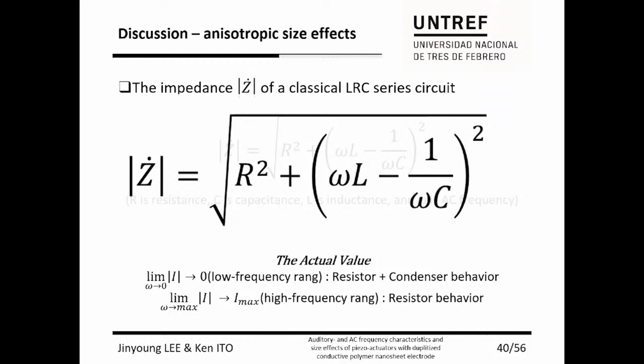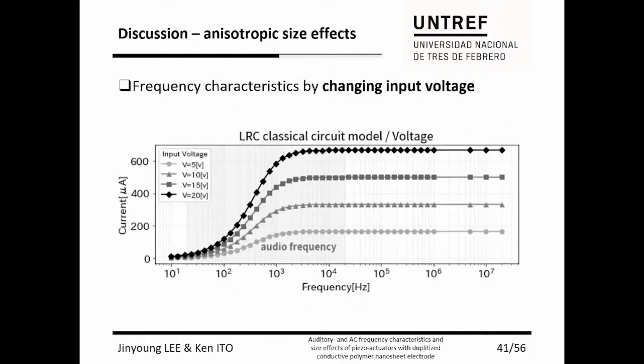In the following, we consider an RC series circuit by assigning 0 Henry to the inductor and 10 kΩ to the resistor. In the classical RC circuit model, the high frequency line shows resistive behavior, so the amplitude of the applied AC voltage is proportional to the plateau current value.